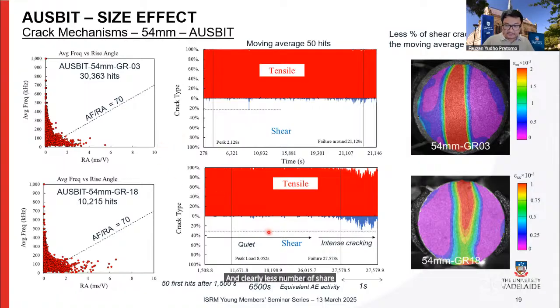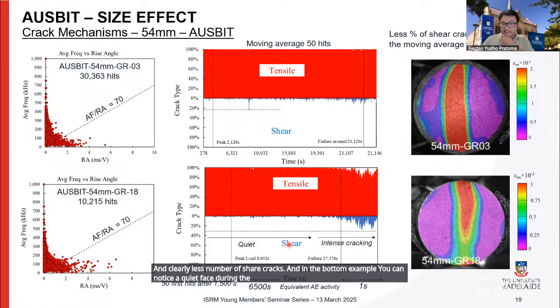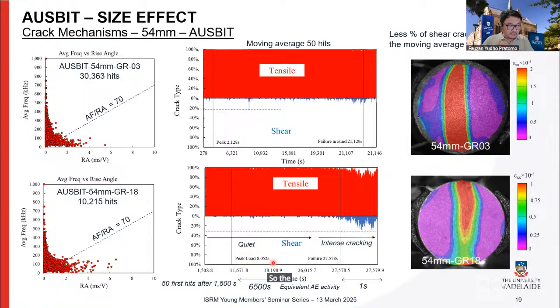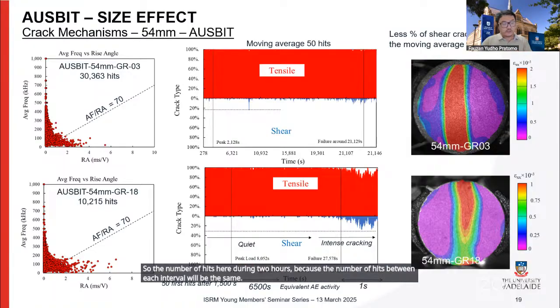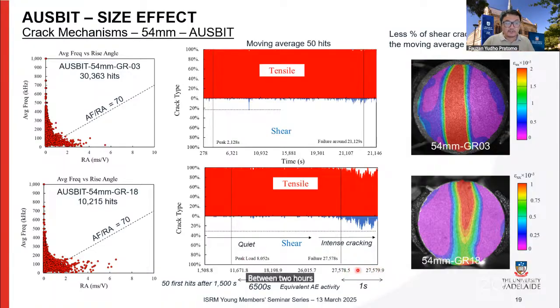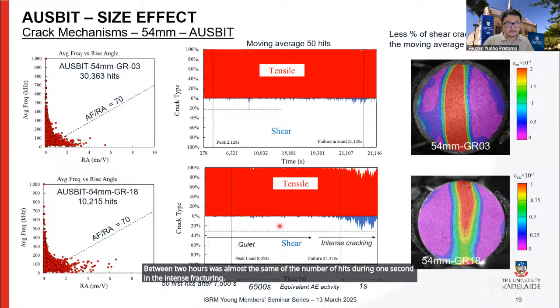And in the bottom example, you can notice a quiet phase during the post-peak regime. The number of hits between each interval will be the same, so the 2 hours here was almost the same as the number of hits during 1 second in the intense fracturing at the end of the test.